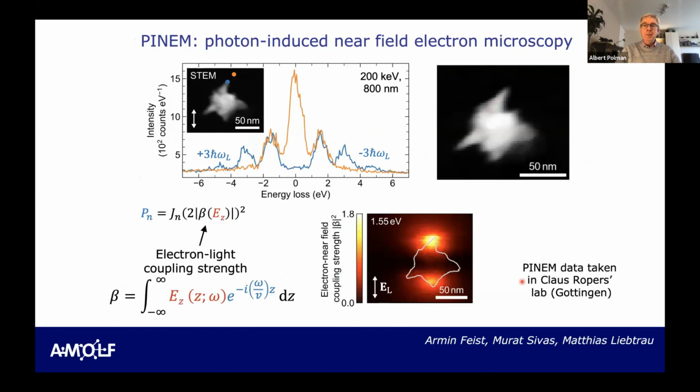And so that's a new area we're getting into, and I just want to illustrate it with, coming to the end here, how we take a nanostar. This is again a nanoparticle, but now with an extremely sharp tip, so there's very strong optical near field. So we zap it with a laser, create this near field, the electron beam goes through, and then here you see in blue how indeed the zero loss is gone, so that's 200 keV in this case, electron. So this is actually done in a TEM. It has lost all its primary energy, or gained photons or lost photon momenta quanta.